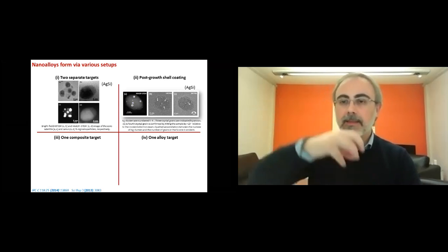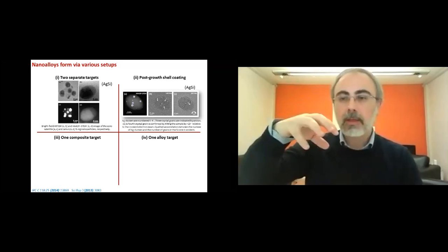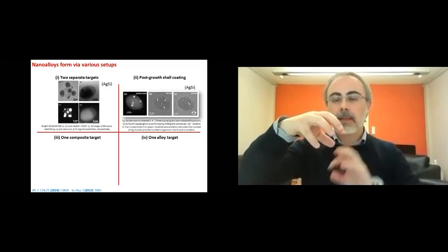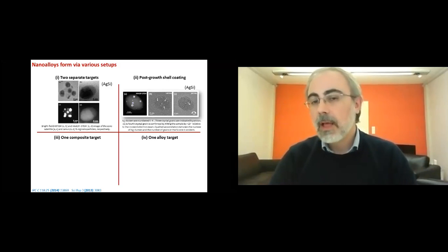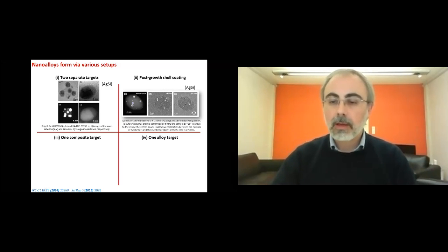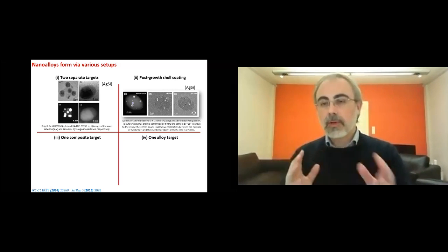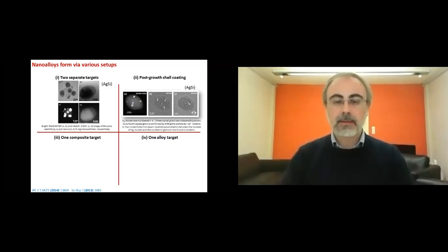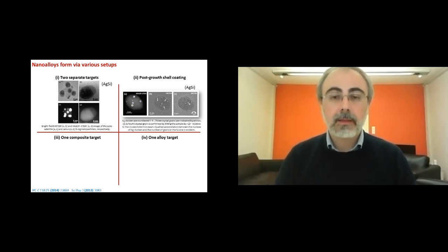The idea is that as each one of these satellites goes to the surface, it induces crystallization in the area around it. And the other one creates another crystallite, and another crystallite. We have done extensive TEM surveys in our system, and we found that every single time the number of crystalline domains in the core of the nanocluster coincided with the number of satellites in the end. So exactly the same material, the two structures look the same. I'm talking about the two cases presented here, but the physical mechanism is completely different, and the end result is also different because of this different mechanism.